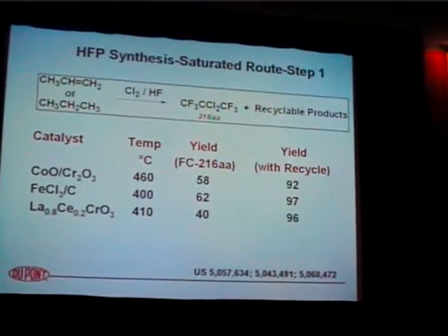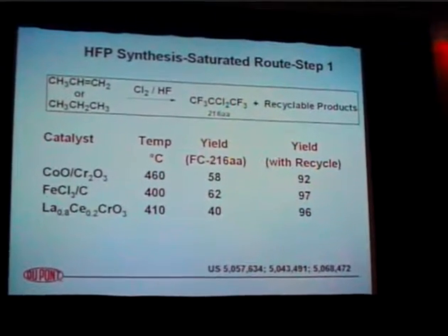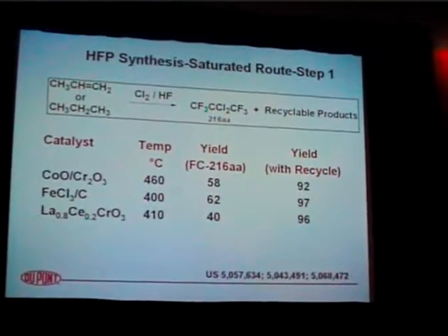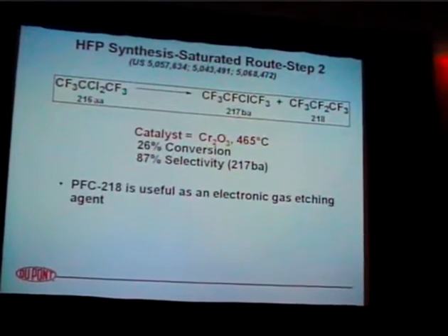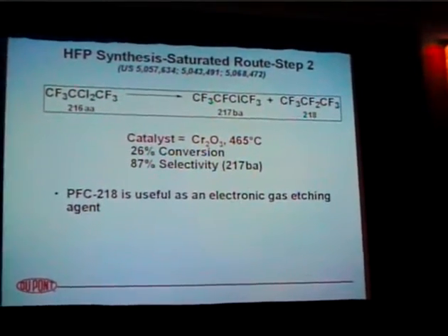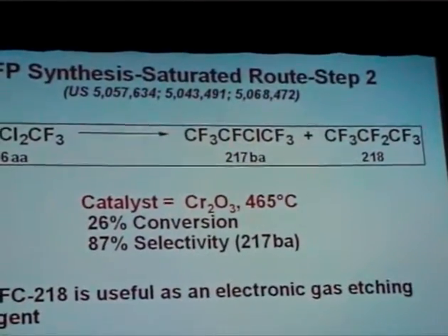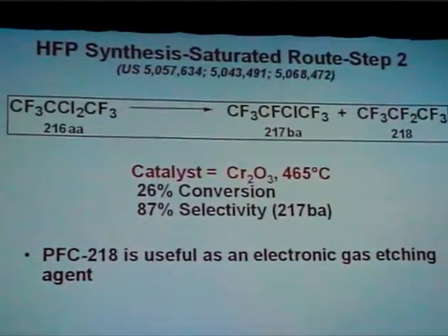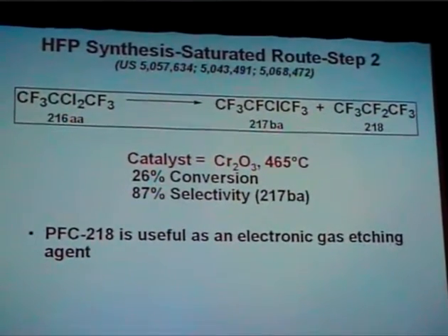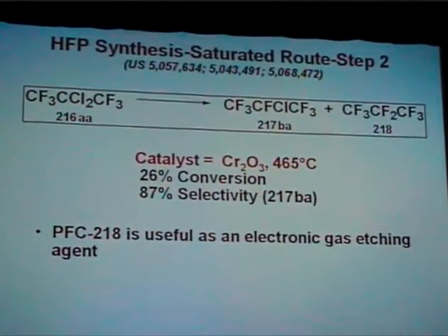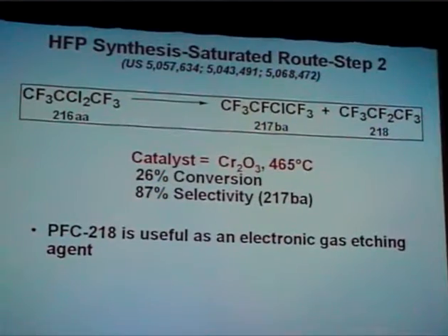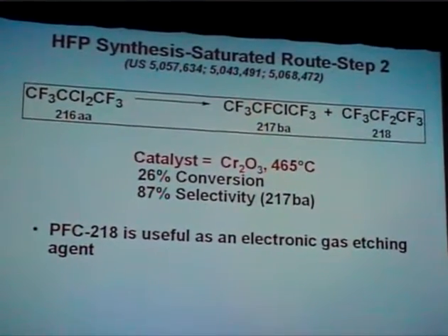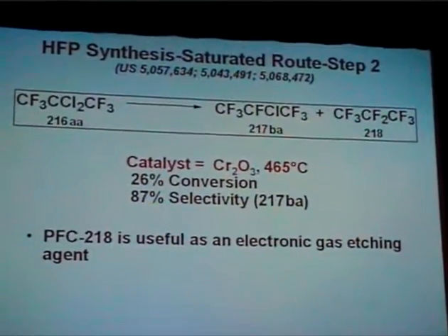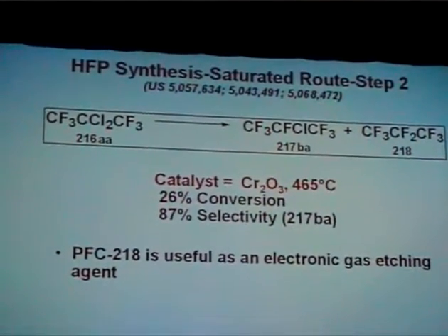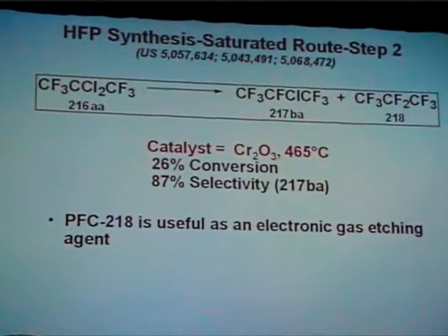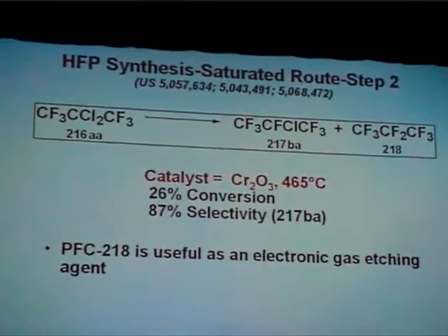Now the next job is to take the two chlorines in the middle and to exchange only one of those with HF to make the chloroheptafluoropropane. And that's done with chromium oxide. It's a difficult reaction. Those two chlorines are tightly bonded. Once you start to exchange one, it's very easy to exchange the second one. And if you're not careful, you'll make perfluoropropane, which is okay. That's a high-value material that's used in electronic etching of silicon chips. But we really wanted to stop the reaction at the monochloro derivative there, the 217BA, and chromium oxide will give around 87 to 90% selectivity at relatively low conversion.